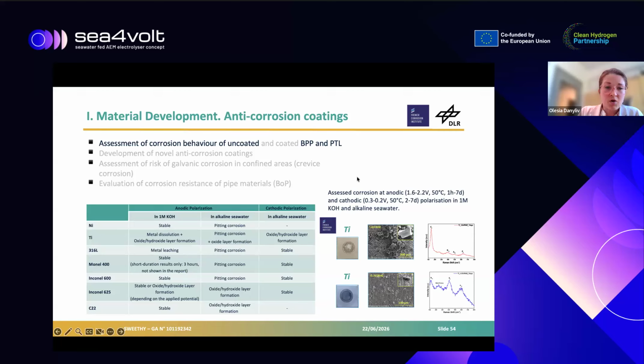So far within this task, we performed the corrosion study of uncoated BPP and PTL, and the same studies on coated BPP and PTL are ongoing together with the development of anti-corrosion coatings. That's why so far I can just show the results on the uncoated BPP and PTL. This is also a public deliverable at our website. You see in the table the metallic substrates that were studied for corrosion behavior, both in anodic and cathodic polarization in 1 molar KOH and in seawater, or alkaline seawater. Next slide, please.